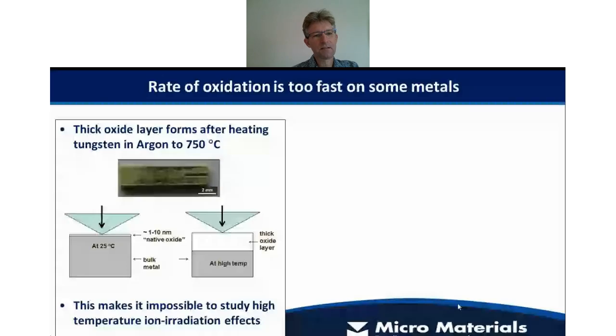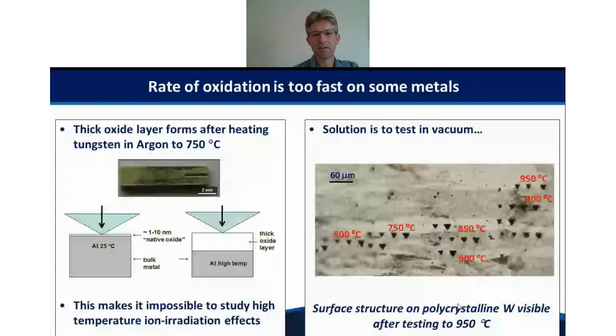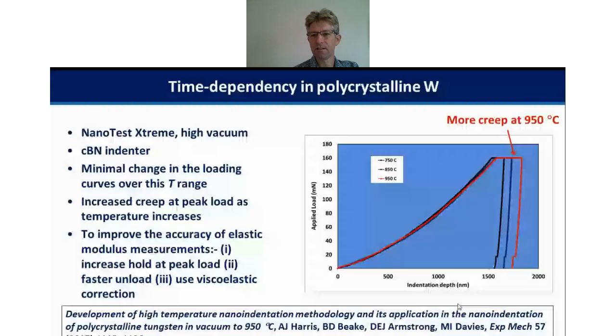So the problem is, though, that if we're trying to test in argon, the tungsten sample oxidizes too fast, and you get the formation of a thick tungsten trioxide layer, as we can see. At room temperature it's not a problem, because there's a native oxide, but it's very, very thin, and essentially we don't see that in the indentation data. But at high temperature it's really thick and porous, and it's certainly not possible to test any irradiation effects. So the solution is to test in high vacuum, as this is an example of the surface structure on a polycrystalline tungsten sample, and you can see the surface structure is retained after the tests.